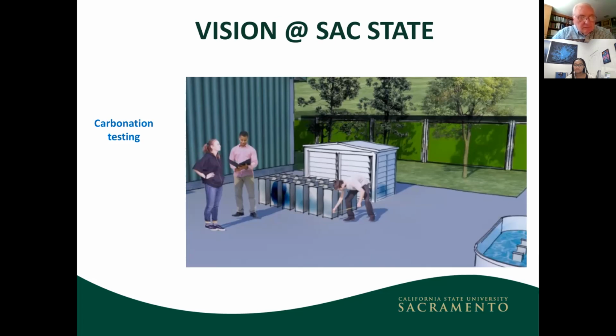It makes the concrete more volumetrically stable, it makes it stronger, and it basically closes down the pore system inside that makes it very hard for deleterious chemicals to come in and penetrate it. So from a concrete perspective, that's a good thing. And like I said, this happens naturally over time. All concrete carbonates, depending on what's exactly in the mix. Some concrete is going to carbonate faster than other concretes.